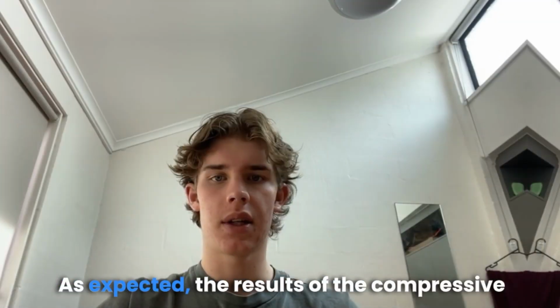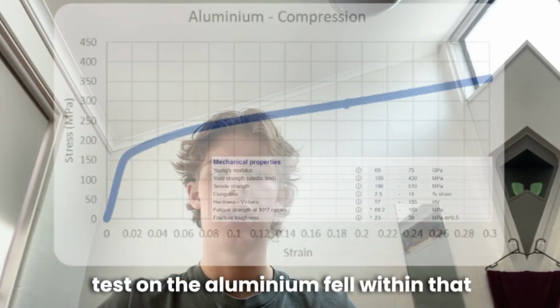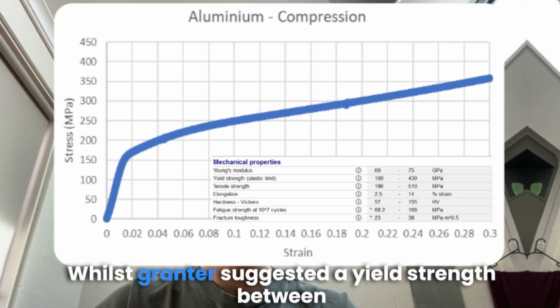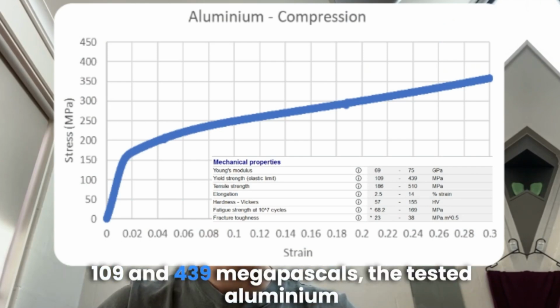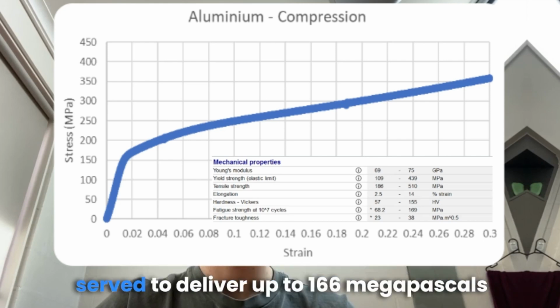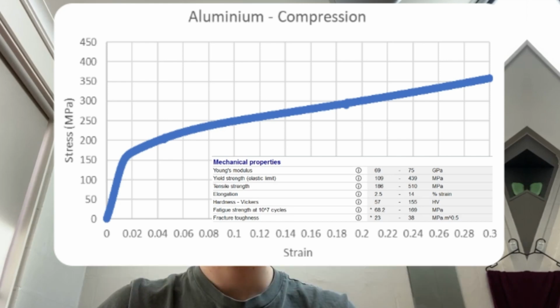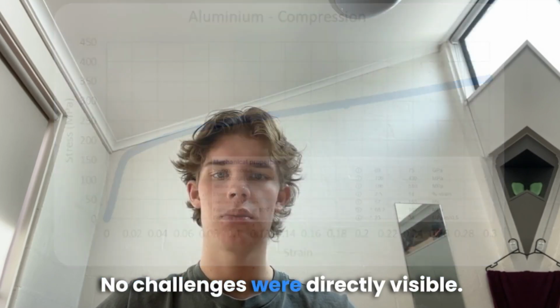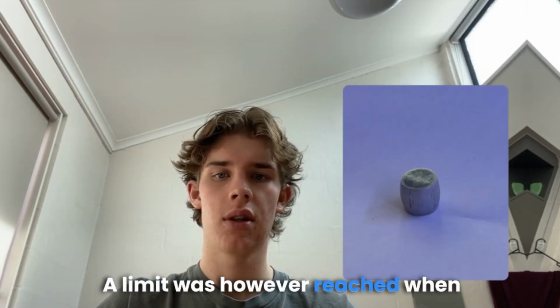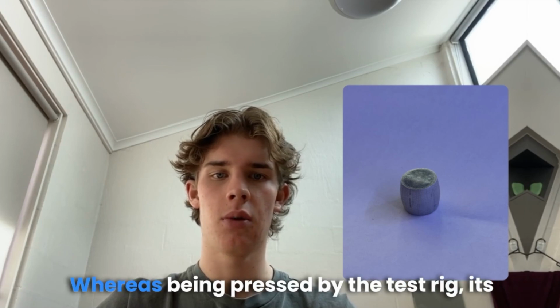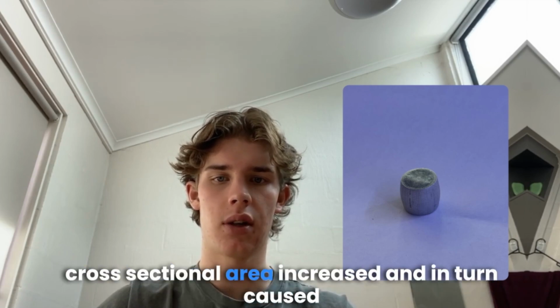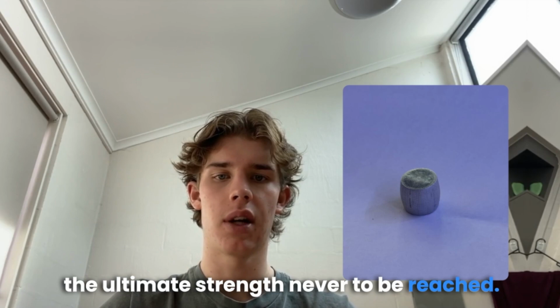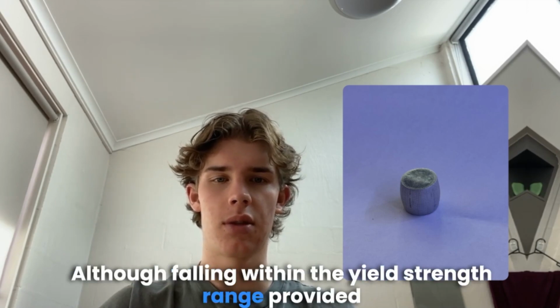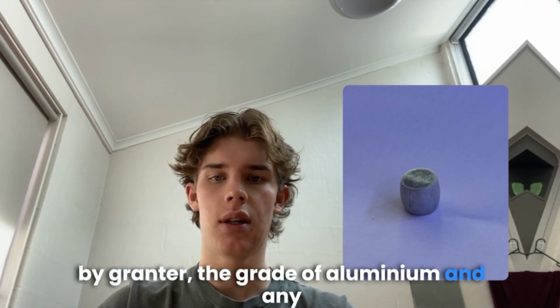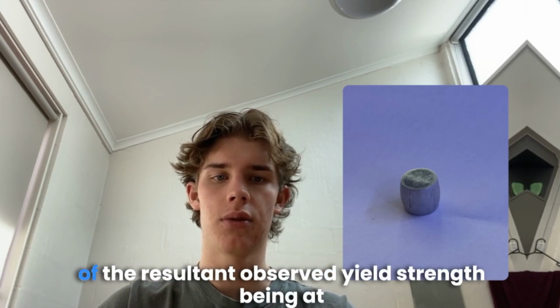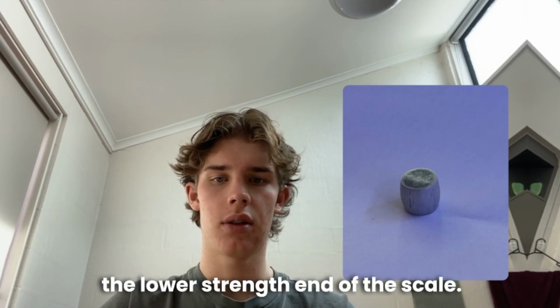As expected, the results of the compressive test on the aluminium fell within that of the theoretical provided by Granta. Whilst Granta suggested a yield strength between 109 and 439 megapascals, the tested aluminium served to deliver up to 166 megapascals. From the testing of the sample, no challenges were directly visible. A limit was, however, reached when the test sample began plastic deformation, where, as being pressed by the test rig, its cross-sectional area increased and in turn caused the ultimate strength never to be reached. Although falling within the yield strength range provided by Granta, the grade of aluminium and any applied heat treatment process was likely the cause for the resultant observed yield strength being at the lower strength end of the scale.